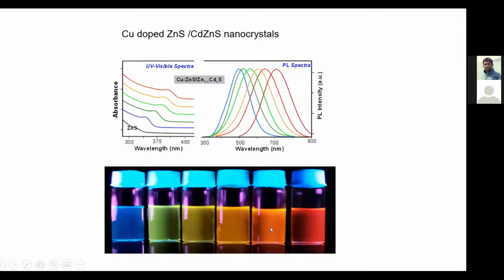And as I showed you earlier, these are the digital images of the nanocrystals dispersed in the solution. It's very dilute, but it's very bright. And you can see we can distinguish by the absorbance and emissions. You can see absorbance here is close to 400 nanometer, but your emission is very far, like 700 nanometer. So this is a good thing, because they do not overlap, so you do not have reabsorption in the solution. So that's why people use the doping. And also you can create a different electronic level and electronic structure.